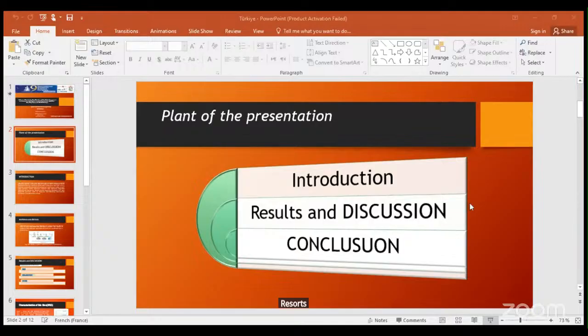Results and discussion. Characterization of thin films: XRD, SEM, EDX, and UV-visible. Figure 2 shows the XRD patterns of pure ZnO films. We observe three strong reflections, 100, 002, and 101, which correspond to the hexagonal wurtzite structure. This result is consistent with previous studies. The intensity of the diffraction peaks decreases with zinc sulfate. The presence of sharp and numerous diffraction peaks indicates the polycrystalline nature of the films.